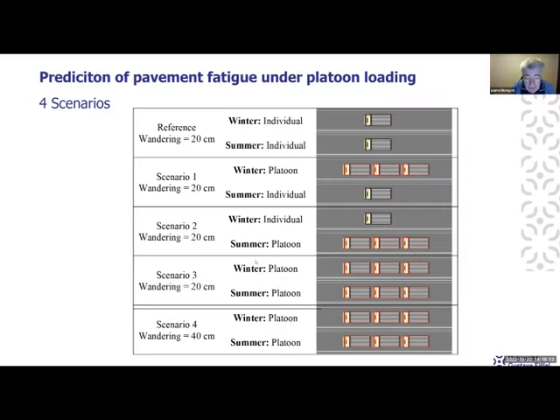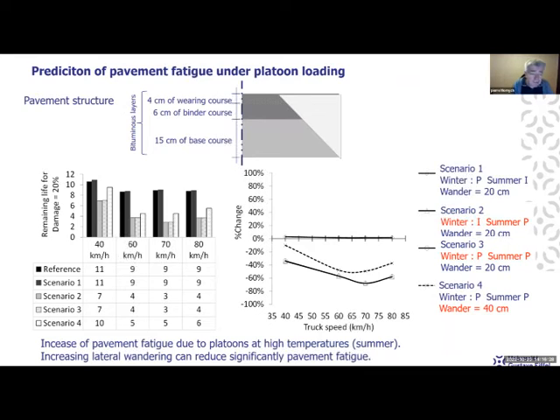In scenario 3, we had only platoons, in the winter and in the summer. And in scenario 4, we also had only platoons, but with a larger lateral wandering, 40 centimeters instead of 20 centimeters. And so we tried to predict the fatigue life with these different scenarios for the pavement tested in our experiment. And here you can see the results in terms of fatigue life leading to a damage of 20%. It's a method of calculation of damage that we use in the French design method.